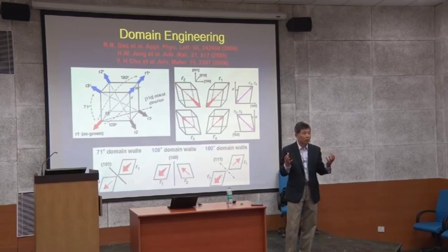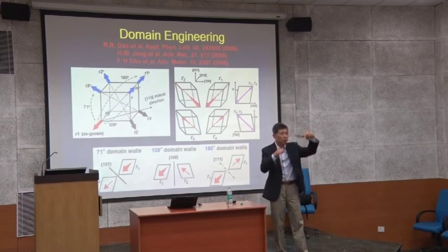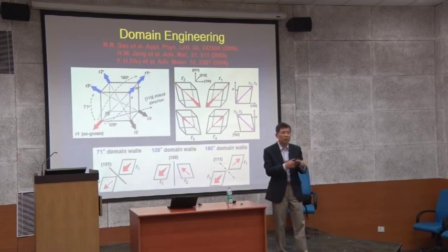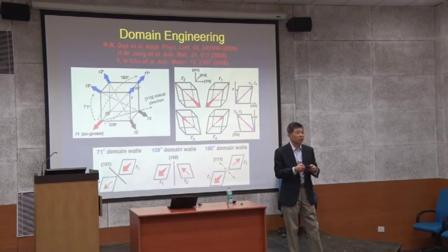Orthorhombic system is not, because the nature of the A, B, and C are not the same, this one and that one not the same. This is the same thing like a yttrium barium copper oxide superconductor. You have twins, okay? Twin formation between this grain and this grain. In between those, we call twin boundaries. Because this one and that one are like a mirror plane. Okay? Mirror plane, that forms the twin boundaries.